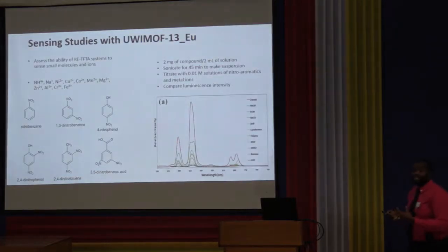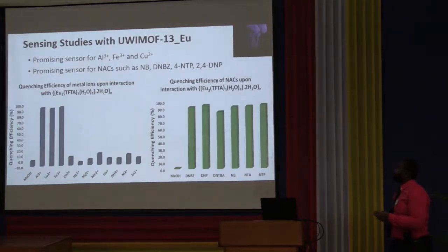Right, so due to the strong photoluminescent properties, we sought to use this as a photoluminescent sensor for metal ions, as well as for nitroaromatic compounds that are used as explosives in bombs. So what we did was to form a suspension of the compound in methanol in this case, and then we added certain amounts of metal ions as well as the nitroaromatics, and looked at the change in the luminescence intensity.